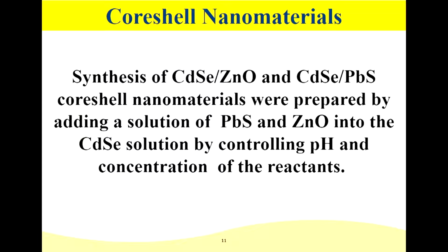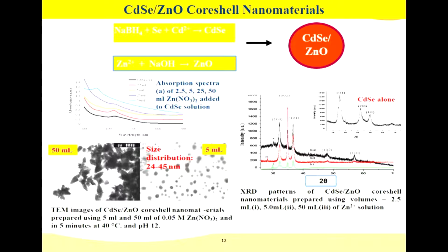So we also looked at the core shells that I described earlier, and in this particular case here we tried to see if we're adding zinc oxide into cadmium selenide and also taking cadmium selenide, adding into lead sulfide, what really happens there. And we found out that when you vary the amount of zinc oxide that is added into the cadmium selenide solution thereof,